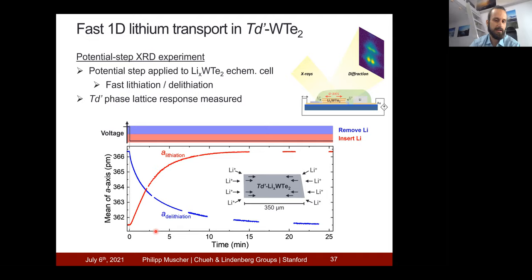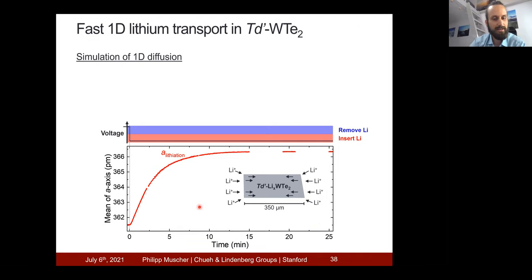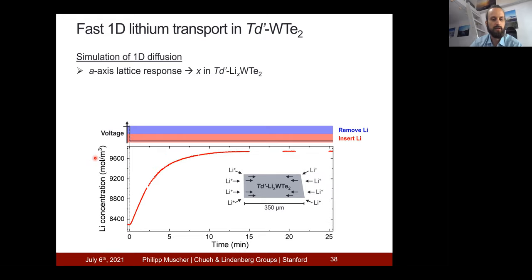So with this data, I can actually use this as an input to calculate the diffusion coefficient. What we know is that the A-axis lattice response, which is measured over here, is directly proportional to the lithium concentration in tungsten ditelluride. Due to this, we can switch this y-axis from the A-axis lattice parameter to the average lithium concentration in the whole flake. And the curve looks the same.